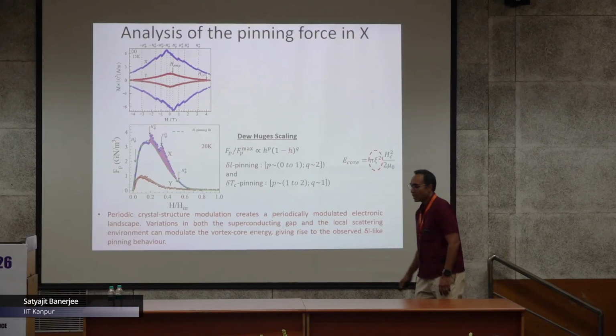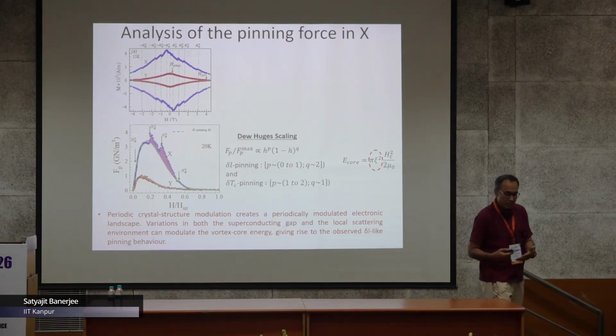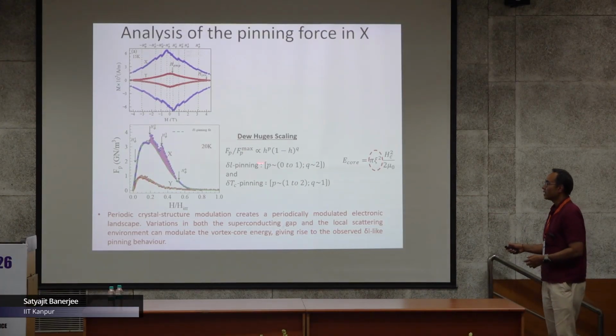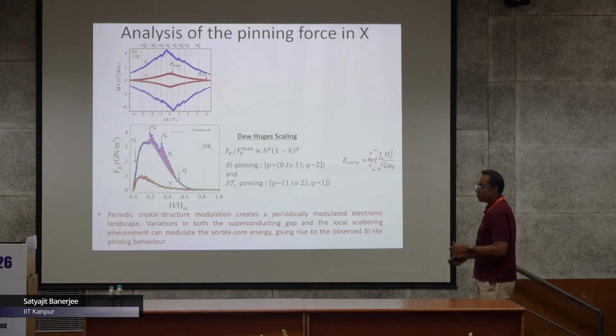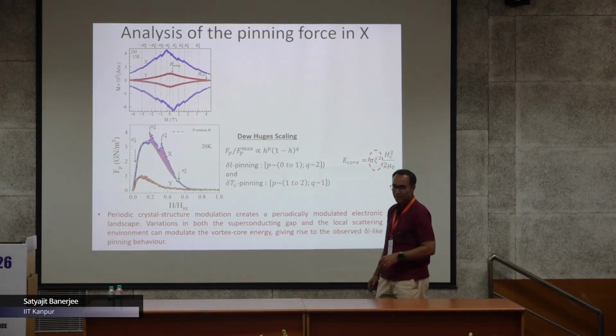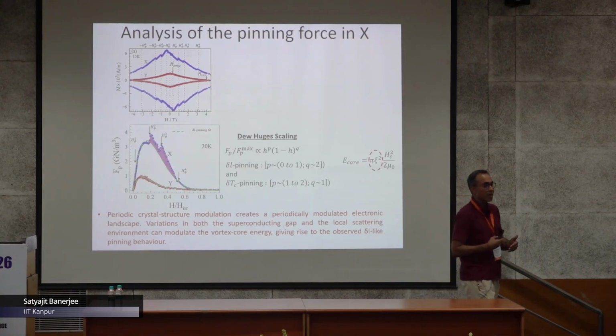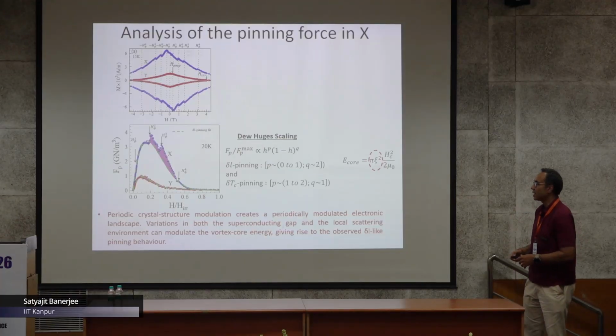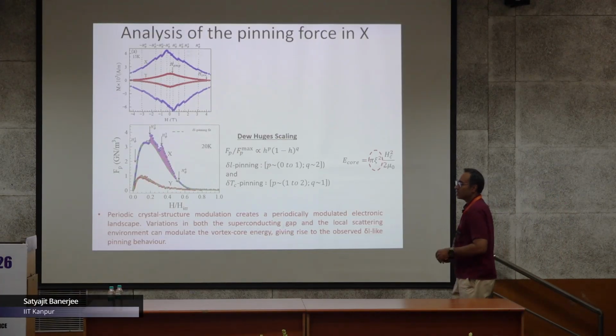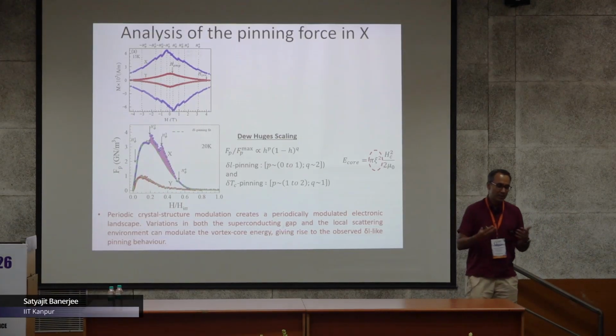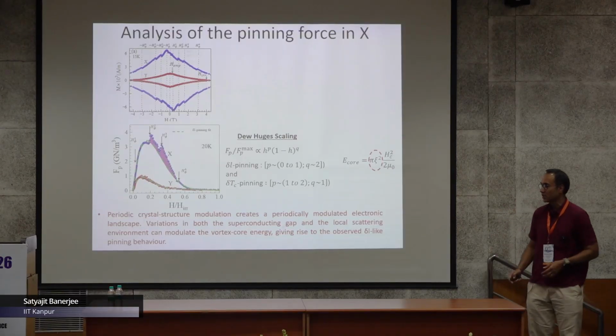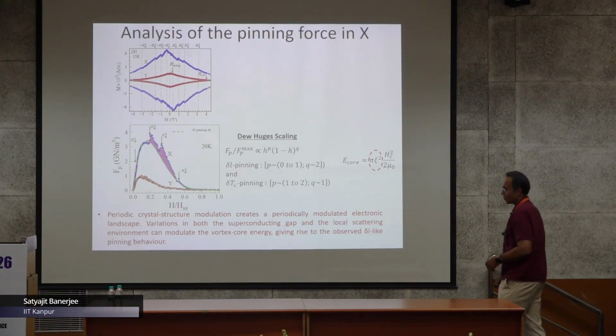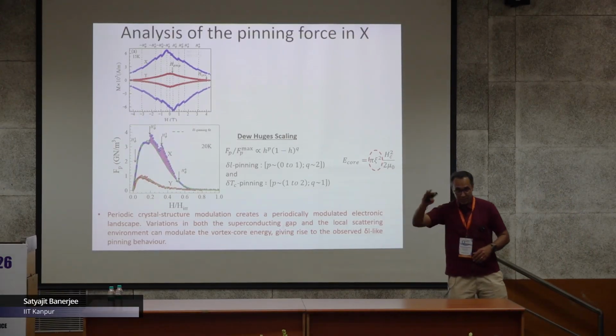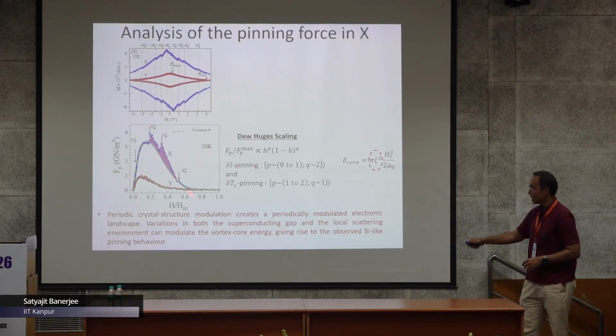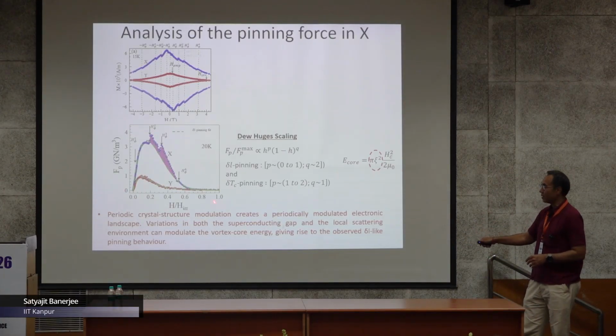The nature of the fit tells you that the type of pinning present inside the crystal is not coming from TC variations inside the sample, but rather from fluctuations in the mean free path of the electrons inside the crystal. This is called the delta L pinning mechanism.